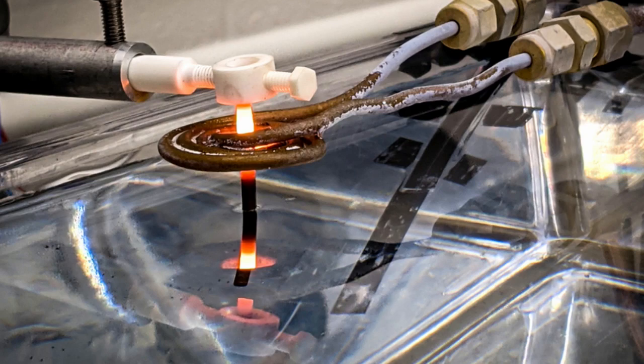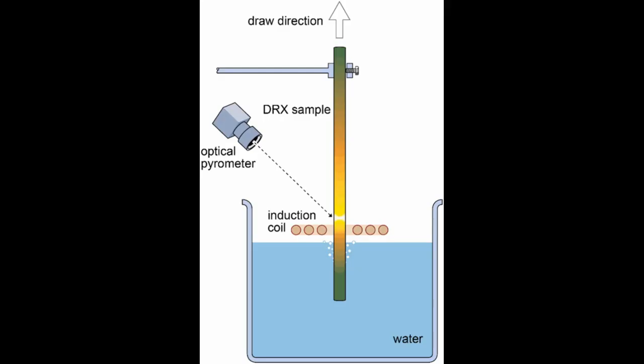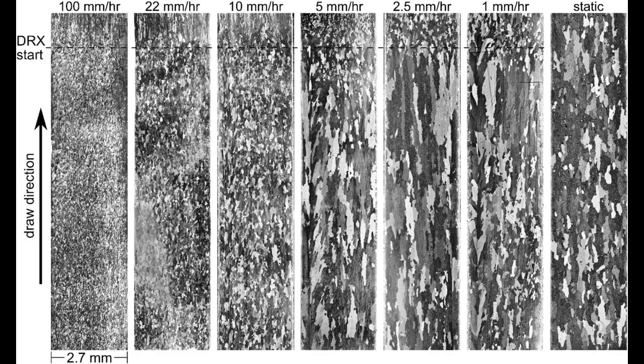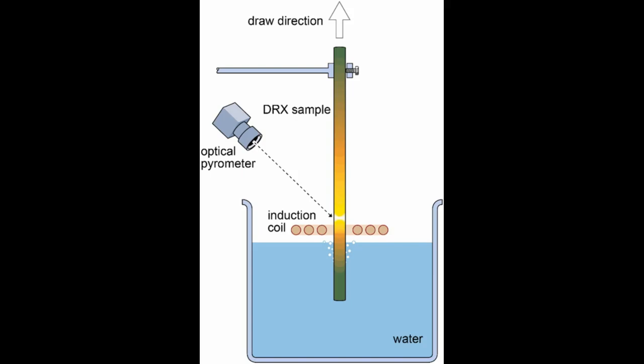The team's new method is a form of directional recrystallization, a heat treatment that passes a material through a hot zone at a precisely controlled speed to merge a material's many microscopic grains into larger, steadier, and more uniform crystals. Directional recrystallization was invented more than 80 years ago and has been applied to wrought materials. In their new study, the MIT team adopted directional recrystallization for 3D printed superalloys. The team tested the method on 3D printed nickel-based superalloys, metals that are typically cast and used in gas turbines.